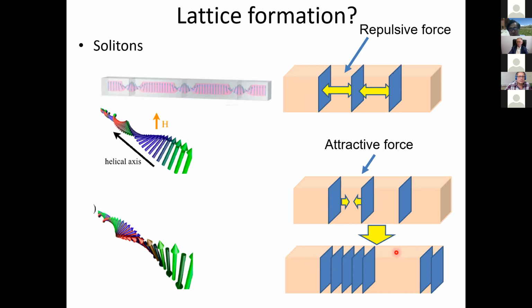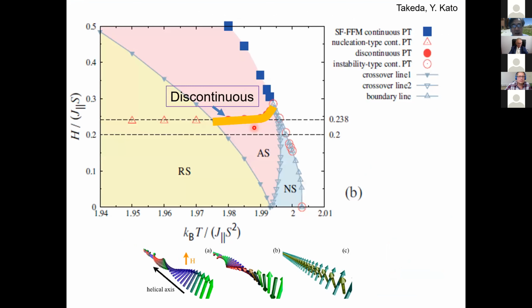In this case, as you can see, it is like ice and water. Here is ice, and water exists at the same time. Ice and water is a first order transition, a discontinuous transition. So this case corresponds to a discontinuous or first order transition, where phase separation occurs just at the transition. Now we clearly know here is something very special: only the anti-ferromagnetic case shows the attractive soliton phase.